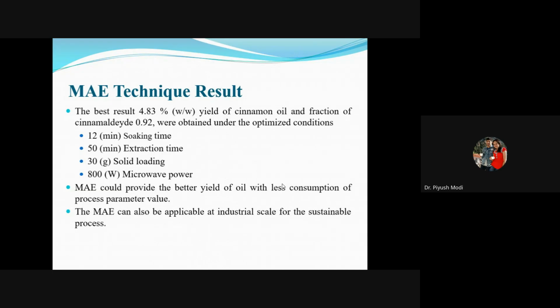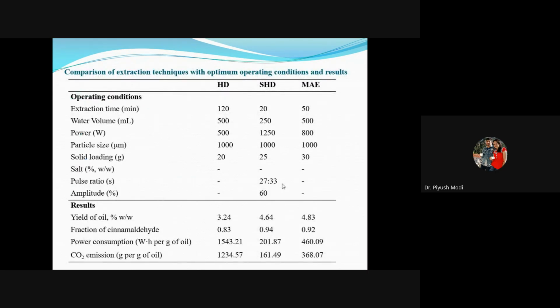The optimized parameters are 12 minutes soaking time, 50 minutes extraction time, 30 gram solid loading, and 800 watt microwave power. We get a yield of 4.83 percent and the cinnamaldehyde fraction is 0.92. So I have studied three methods, and you can see the results.